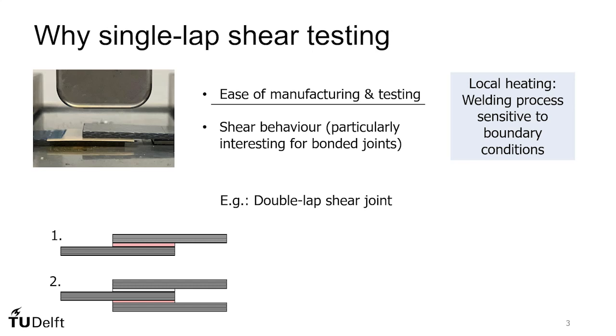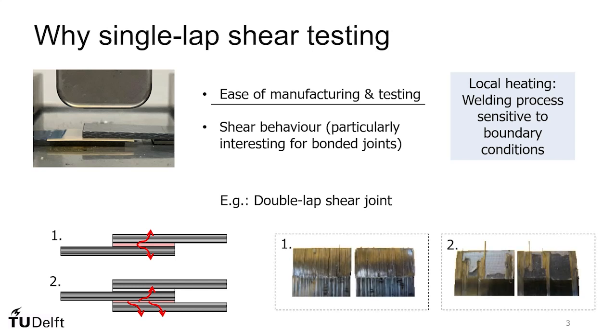However, if we consider the heat transfer problem, we can see that the first and second welds have different boundary conditions. Hence, we will most likely need different welding parameters to achieve the same weld quality in both cases. This is illustrated by these fracture surfaces that indicate quite different failure behavior when the same welding parameters were used to obtain the two welds in the double lap joint.